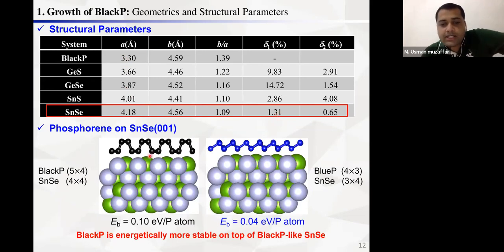So these are the relaxed structures of black phosphorene on SnSe and blue phosphorene on SnSe. The total energy calculation results reveal that the binding energy of black P is relatively higher than that of blue P. It means that phosphorene prefers to stay in a black phosphorene-like structure. So partially it fulfills our expectations. So to further